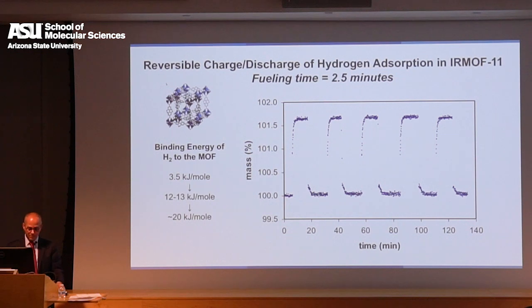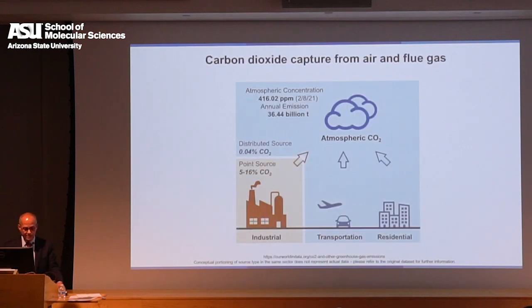So for those of you who are interested in this problem, we need to think of strategies of how to functionalize the interior of the MOF to increase the binding energy of hydrogen to the MOF, to go from 13 kilojoules per mole to 20 kilojoules per mole. Do you think it could be done? If anybody's going to do it, it's going to be in the MOF field because we can control these on the molecular level. Okay, I think that's the key development here on a fundamental level, that we can control matter in infinite directions on the atomic and molecular level. The CO2 problem is potentially more complex to solve, but it gives me even more hope than hydrogen.